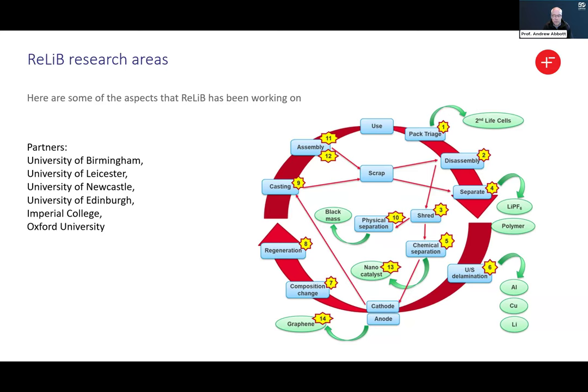We've also looked at ways of upcycling graphite to graphene, changing the chemical composition, regenerating, and the important bit about that regeneration is it has to be a low temperature process to be able to get an economical process and also to have a minimal LCA impact. We've then looked at novel ways of casting these materials with hopefully better binders than the PVDF that's currently used, and ways of assembling them into new pack designs.